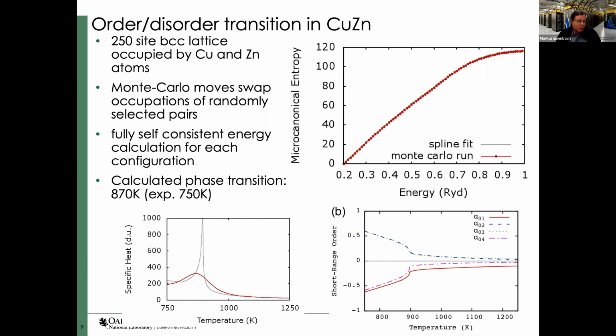Again, we have to note, because of limited computing resources and complications of displacing atoms in the LSMS code at that time, this calculation does not include the lattice vibrations here. So just the configurational entropy basically contributes. But we nicely are able to identify the phase transition, and especially the short range order, if considered as distance from the phase transition, very nicely agrees with experimental values.